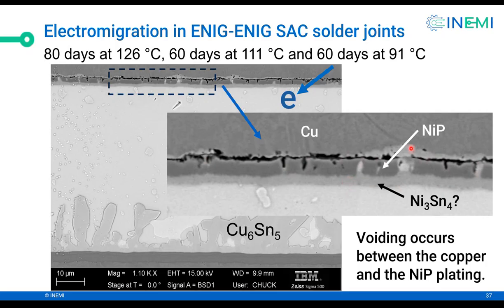And the fact we have Cu6Sn5 here just proves that the copper got into the tin from the top, because the copper is flowing down into the solder. So notice voiding occurs between copper and the nickel. So voiding is here between copper and the nickel phosphorus plating. So porosity happens because less atoms are reaching the interface and more are leaving. So that's the fundamental reason.